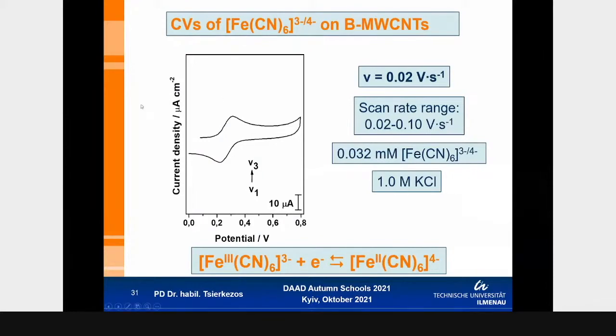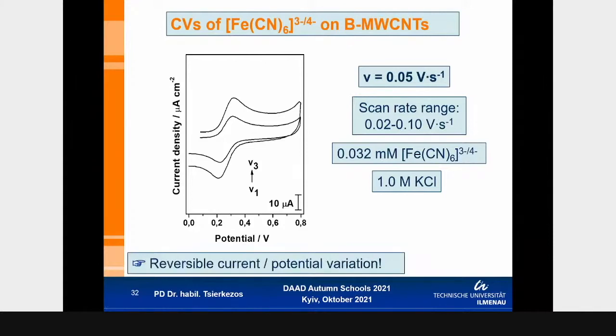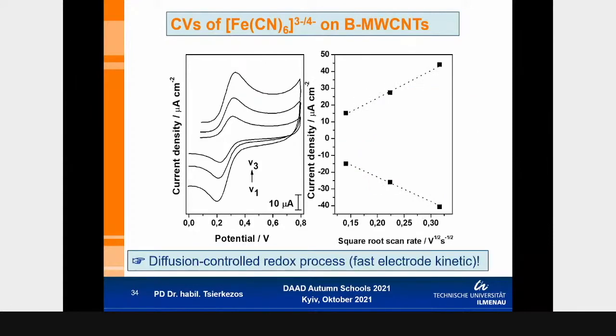And afterwards, I have used this as a working electrode for detecting this system in an aqueous solution of potassium chloride with this concentration. I show now as a representative example the CVs which have been recorded in boron carbon nanotubes. For other systems, they look almost the same. So I did standard measurements like, for example, recording this system at various scan rates, and I observed actually a reversible and diffusion controlled process which was expected for this redox system. So I prove actually that the response of my electrode is quite fast.